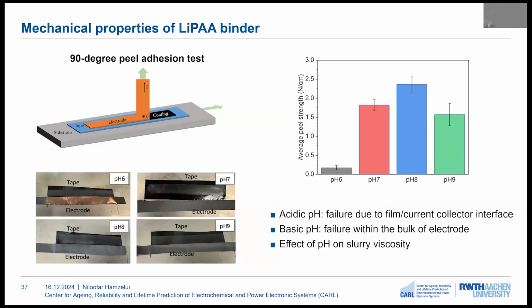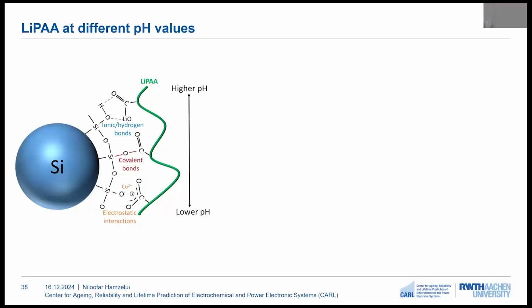Also, it should be noted that the pH of the binder has an effect on the viscosity of the slurry. So for lower pH binders, we are seeing a lower viscosity and therefore more difficulty in coating the electrodes. And at higher pHs, we also see a more viscous slurry, and this also brings a difficulty in terms of coating. Therefore, there should be a balance between the peel strength and also the viscosity of the binders, which in this work, a neutral binder between 7 and 8 was chosen as the optimized pH of LiPAA.